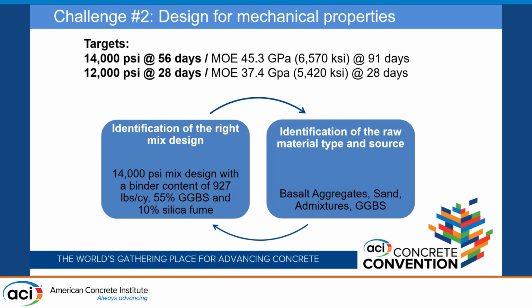For the 12,000 PSI design, the project requirements were at 28 days with a modulus of elasticity of, I'm sorry, 37.4 GPa. And the design that was placed achieved an average of 13,000 PSI and 45 GPa or 6,500 KSI on average. It's important to note that the project team wanted to exceed, and needed to exceed, the design requirements for the optimization of this mix to work.